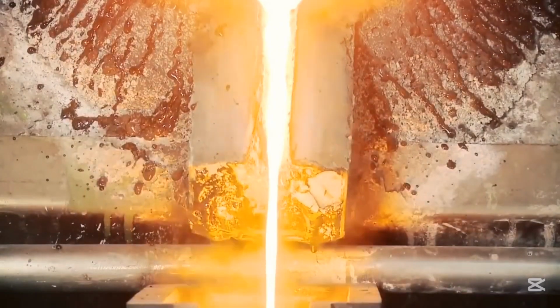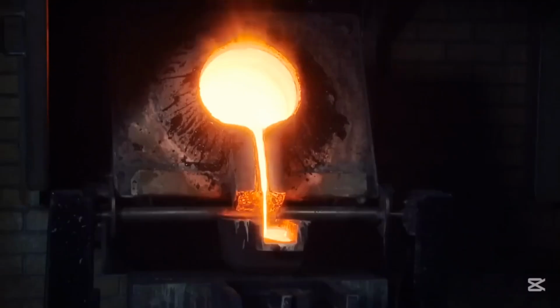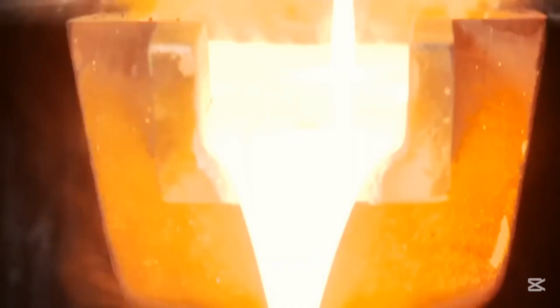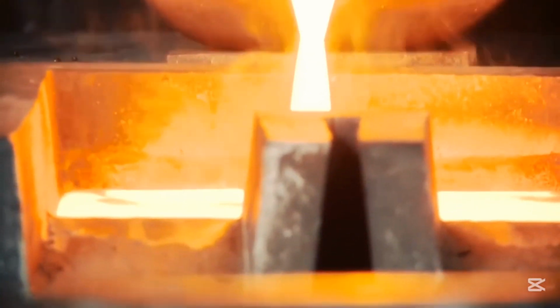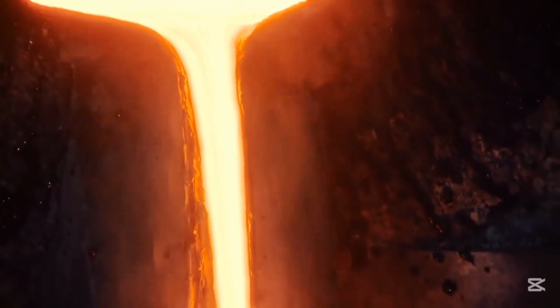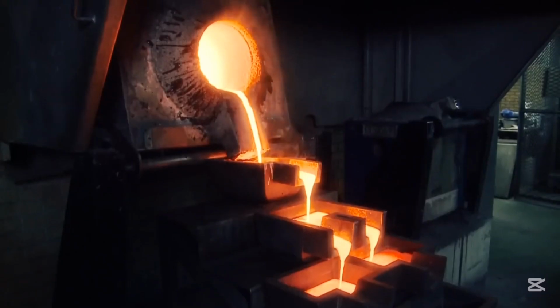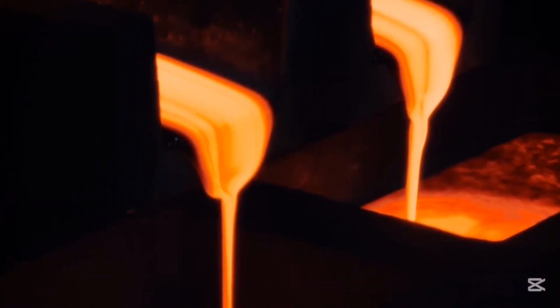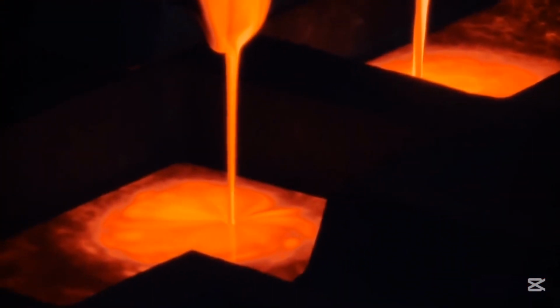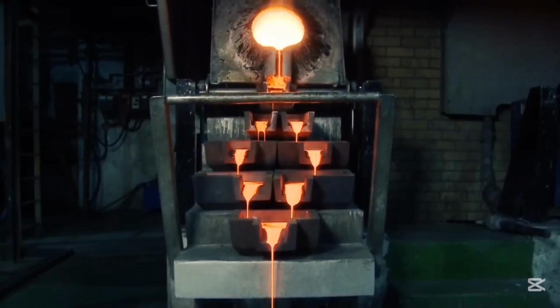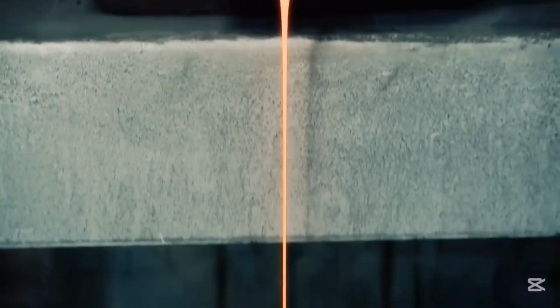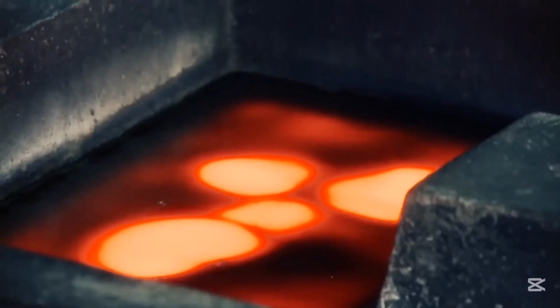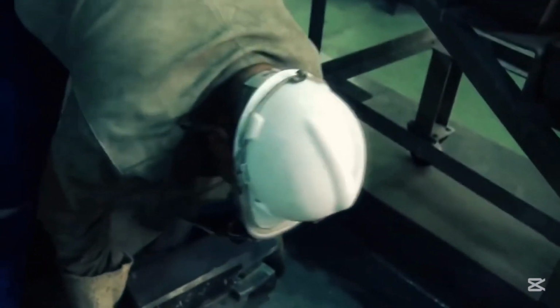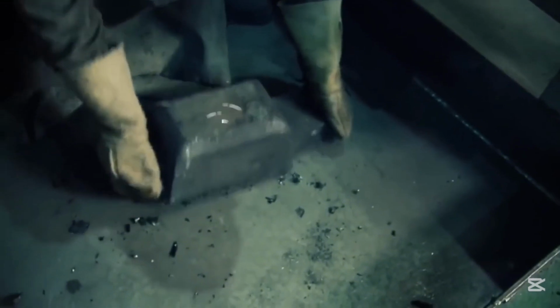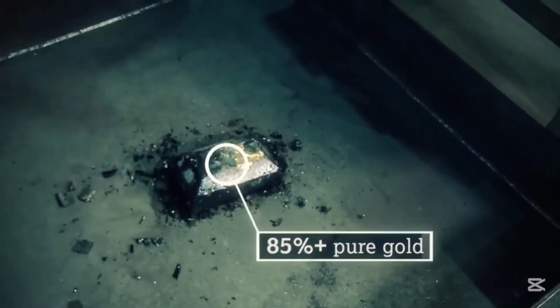Once the ore has been extracted, it is transported to a processing plant where it is crushed, ground, and treated to extract the gold. The specific methods used depend on the type of deposit and can include cyanide leaching, gravity separation, flotation, or carbon in pulp processing. After the gold has been extracted from the ore, it is typically sent to a refinery for further purification. The most common refining methods are the Miller process and the Wohlwill process. Once the gold has been refined, it is ready for sale to customers.